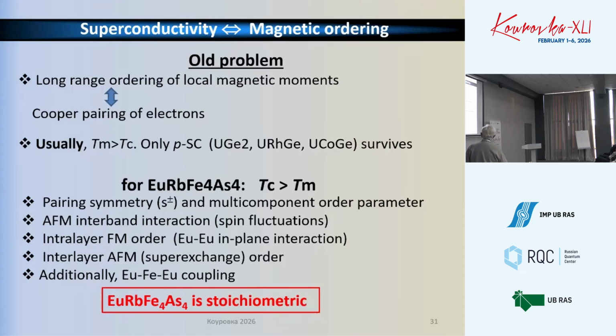For all these materials, which are representative of the class of iron pnictides, the pairing symmetry is believed to be S plus minus and happens mainly as a result of spin fluctuation. And the order parameter is multi-component, as in any other multi-band semi-metal. As I already explained, the intralayer ordering is of ferromagnetic origin because the europium atoms sit close to each other, and the interlayer ordering is antiferromagnetic. It's an interesting issue to discuss who is actually responsible for this superexchange order. Additionally, there is a europium-iron coupling, but it is a second order effect.